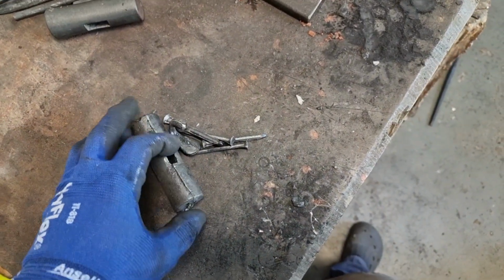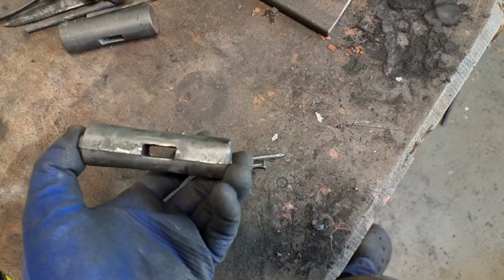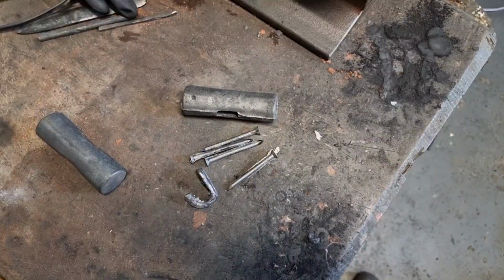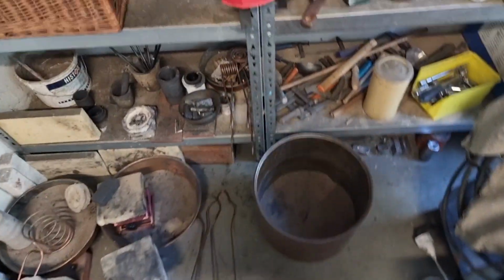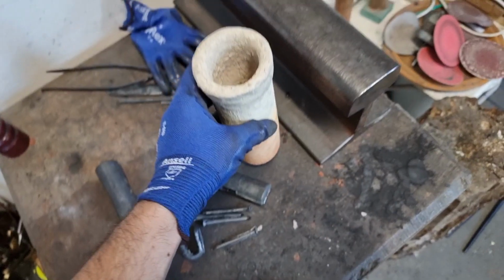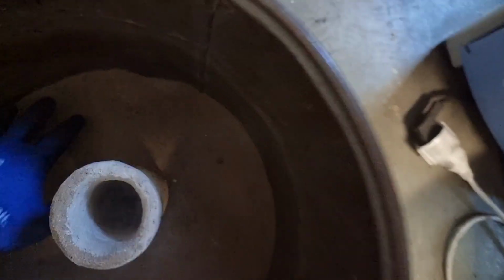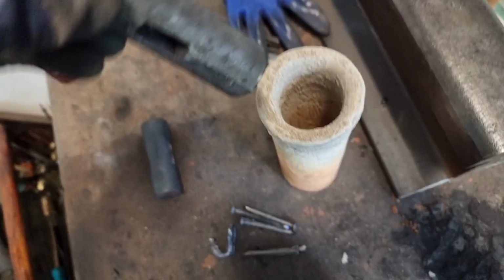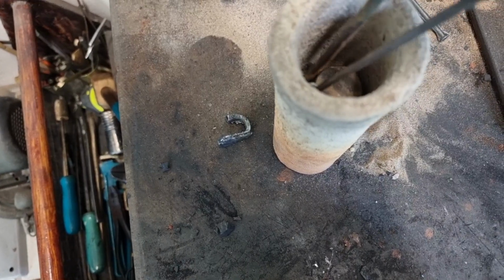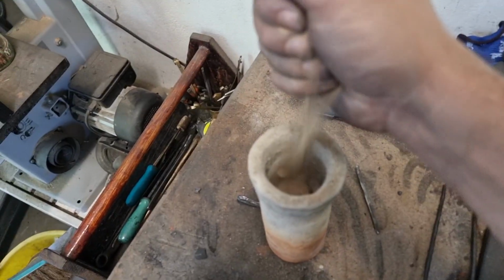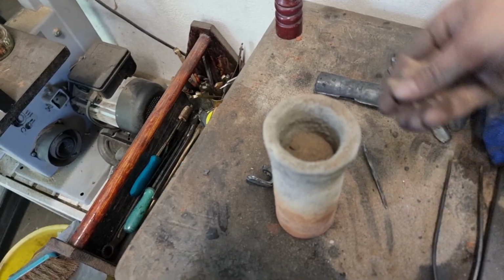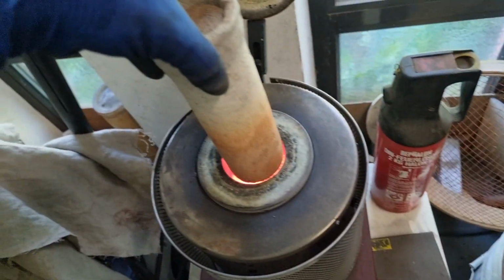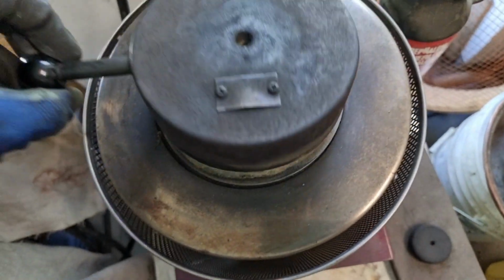Yeah, so the next step was to heat treat that hammerhead, the white cast iron hammerhead. For that, I took a ceramic crucible, a heat-resistant ceramic crucible, and filled that with a thin layer of sand at the bottom. Then I put my hammerhead inside together with the nails, and then filled the remainder of that crucible up to the top with some more sand so that everything was covered neatly with the sand. And then I put it all in my furnace for the heat treatment.